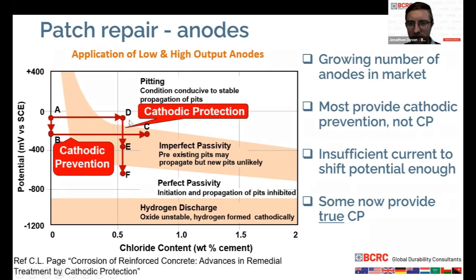And once you've reached that phase, you then need to achieve a big enough potential shift of the reinforcement. If you're going to try to protect the reinforcement using anodes, you need to achieve a big enough shift to go all the way down to F here, the zone of perfect passivity, which means, you know, you've got to get the reinforcement potential down around minus 700 millivolts. Otherwise, if pre-existing pits are already there, they will still propagate if you don't achieve that full potential shift. And a lot of these cathodic prevention anodes that are available in the market just don't have the power to achieve that amount of potential shift. They would only achieve a smaller amount of potential shift and get you into the zone of imperfect passivity.